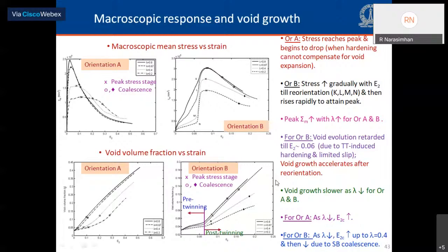This also manifests in terms of the void volume fraction variation. If you look at the bottom two figures, in the case of orientation A, the void volume fraction evolution simply gets retarded as lambda decreases, just like it would happen in isotropic plastic solids. Whereas in orientation B, during the pre-twinning phase, there is a marked retardation of void growth rate, and that is because of activation of fewer slip systems and due to high hardening imparted by twinning. But once the reorientation of the lattice happens, additional slip systems get triggered and the void growth rate increases.